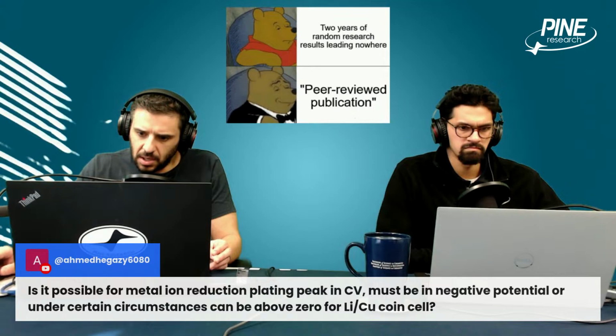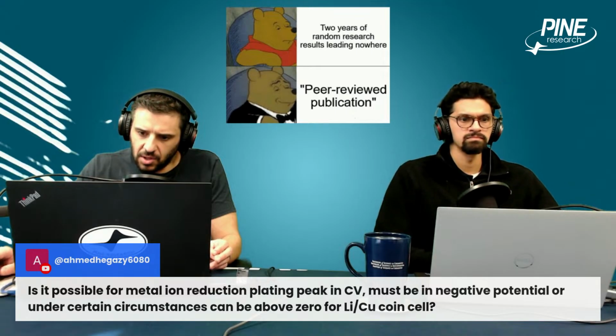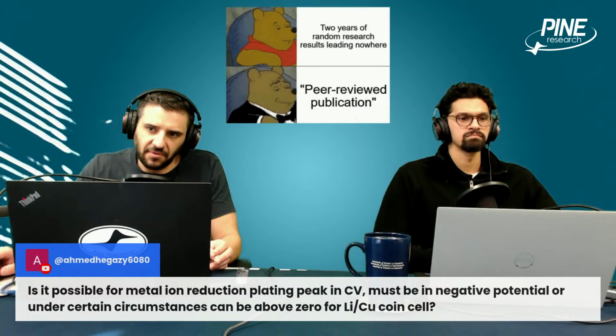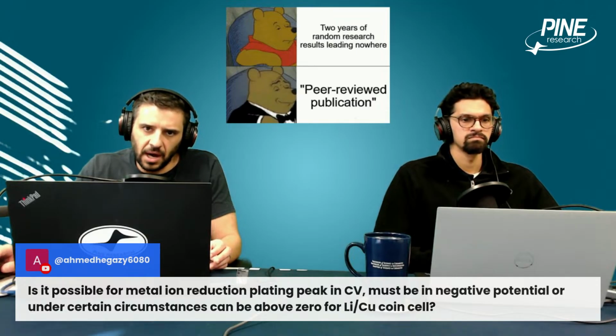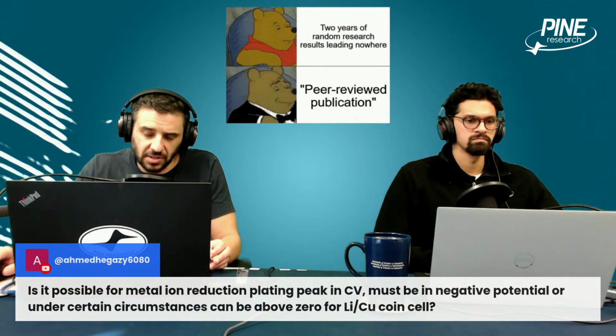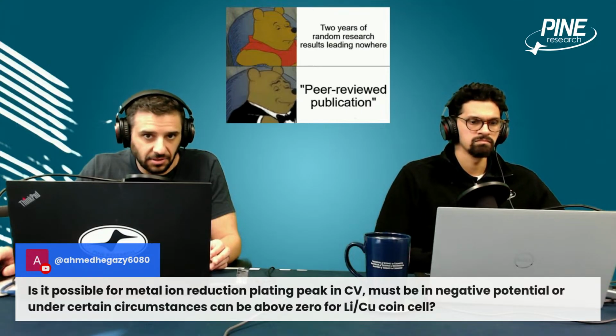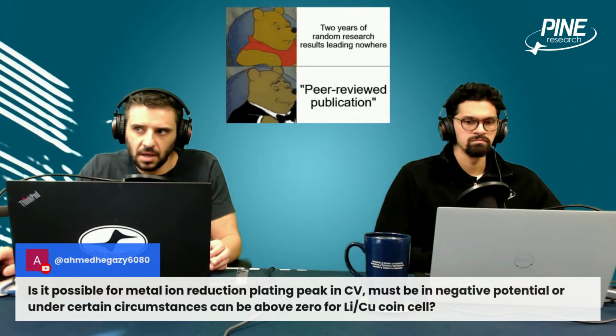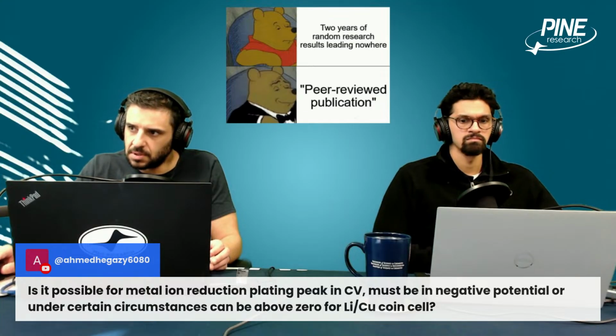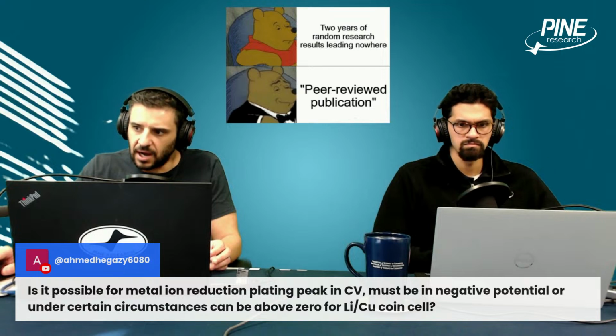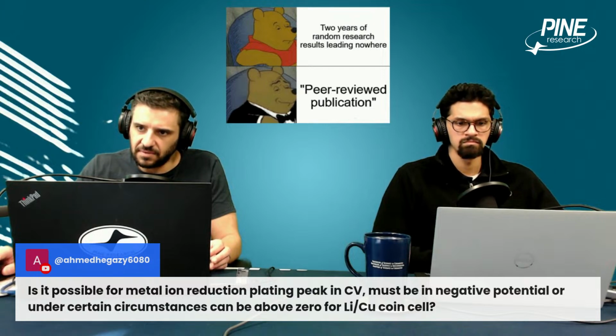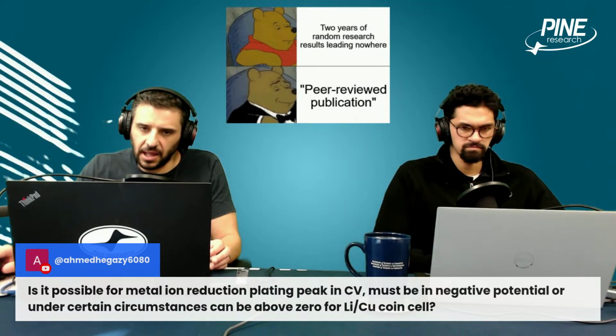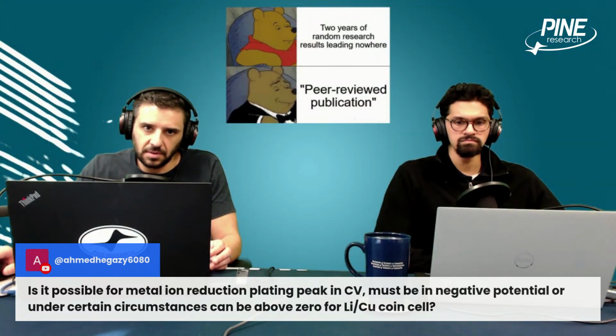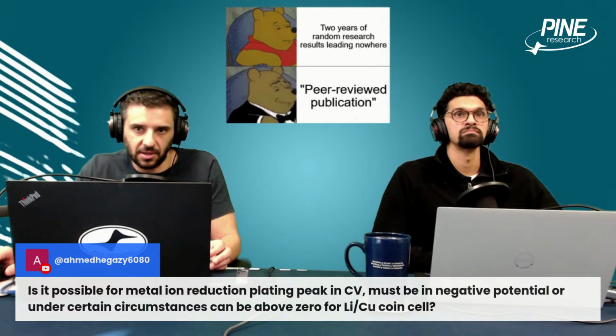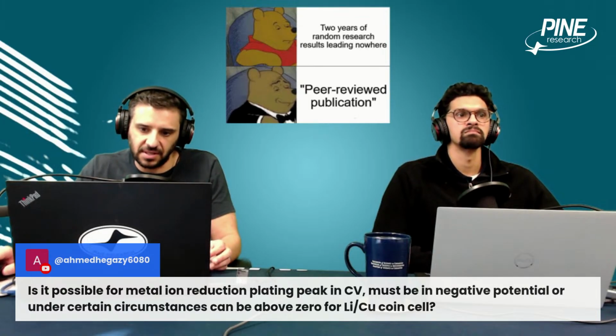So, if you're looking at versus Li plus, everything is pretty much above 0. I wouldn't expect a negative potential versus lithium plus if the lithium is your counter electrode in this case. Everything should be above 0. Almost always. I wouldn't expect a negative potential very often versus Li plus. Li plus has a -3 volt standard potential, and so when you subtract that, you get positive.